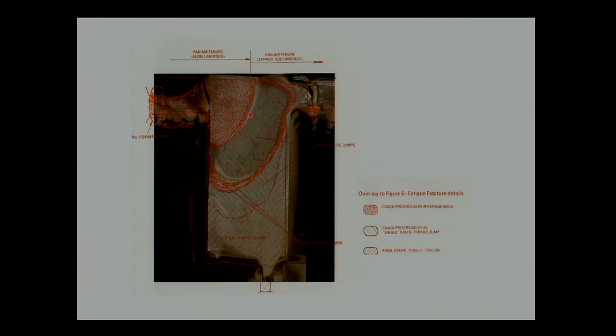When it reached here, there's a static jump where the crack propagates very quickly from here to there. Okay. And then the crack gets arrested again, and went through a bunch of fatigue cycles, but also had some, like over here, you can see some small static jumps, and then eventually it has another static jump that's probably right before it crashed. So it had that jump, and somehow it gets arrested for a very short period of time, and then eventually the whole thing breaks.